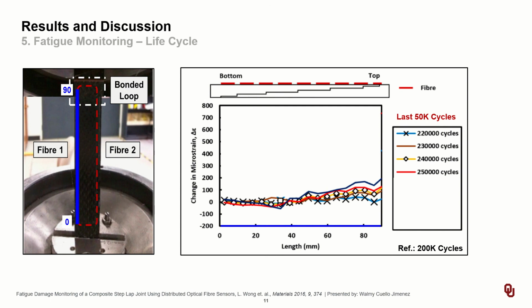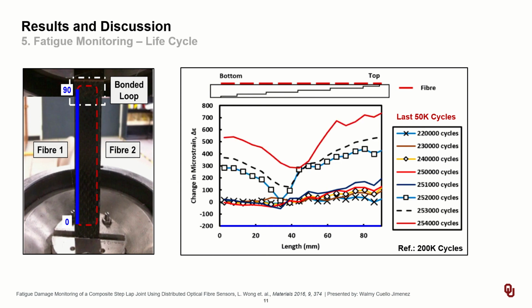Now, the disbond or progressive bond failure can be attributed to the increase in strain with the increased number of cycles. Eventually, in the last 4,000 cycles of the loading scheme, cracks are attained from both sides, top and bottom, of the bonding interface, as seen during the cycle ranges from 252 to 254,000 cycles. All combined prove that distributed optical fiber sensors could be ideal for damage assessment and monitoring of fatigue crack growth along the bond lines.